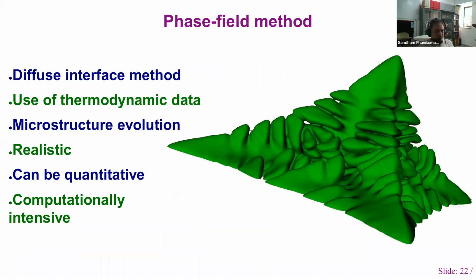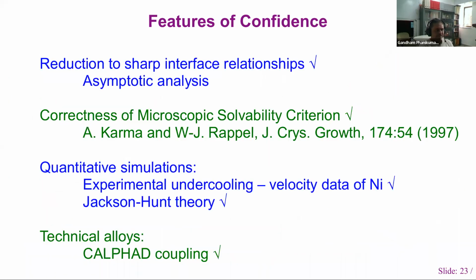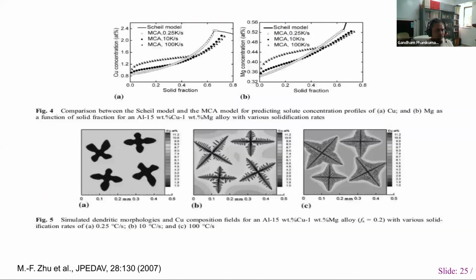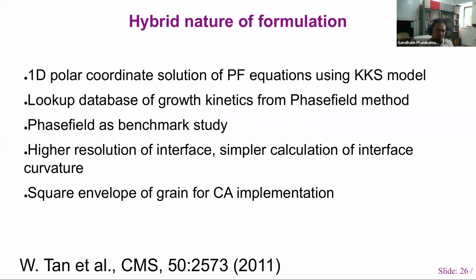Now you can also use those same concepts to relate to microstructural simulations. As I mentioned to you, the phase field simulations can be done, and you can combine them to have the predictions of the segregation patterns, and these can be related to additive manufacturing quite easily, because the difference between casting or solidification welds versus additive manufacturing is only in terms of velocity.